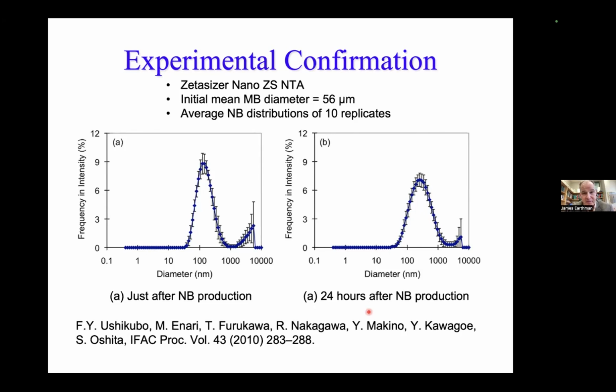The mean microbubble diameter they start with was 56 micrometers, so even above the 50 micrometers in size, but anything larger than 50 micrometers won't shrink, so it won't form a nanobubble, according to our theory. And if you look at the maximum size here, this is just after production, it maxed out right about at 1,000 nanometers. A little bit later, 24 hours later, you can see, it's right around 1,100, where you would expect from our theory. So that was pretty good confirmation. I was pretty excited with that.